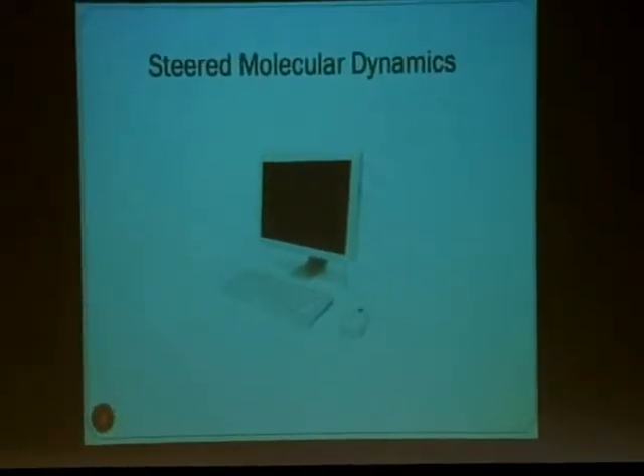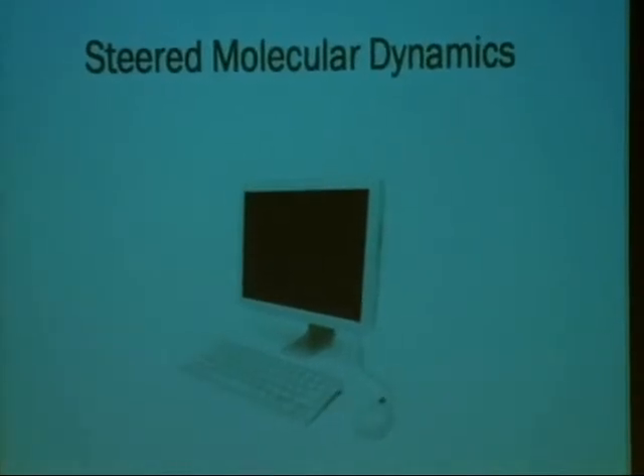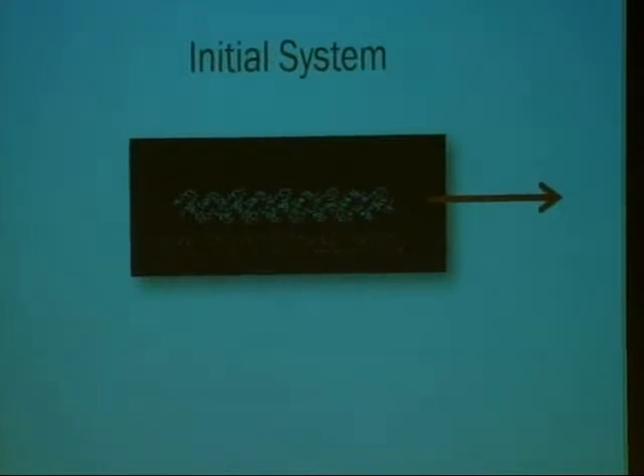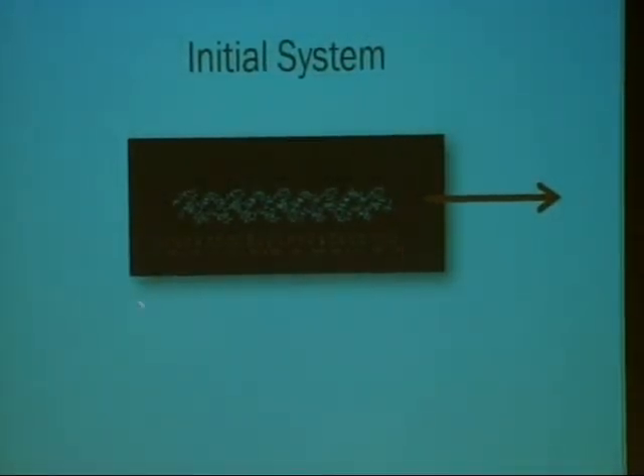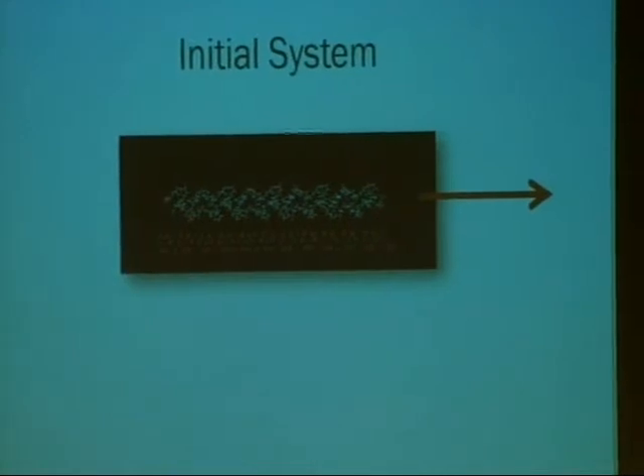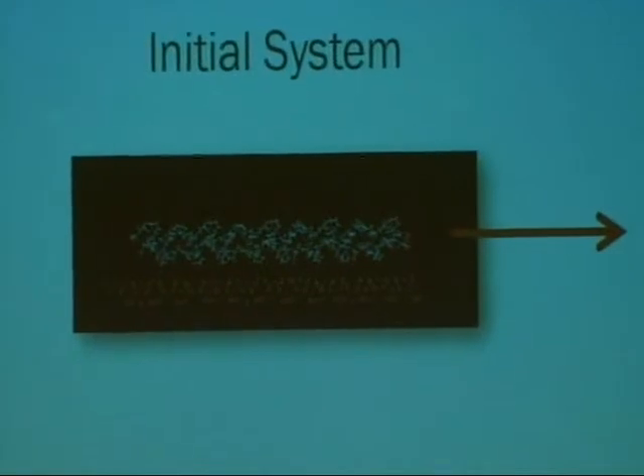To do this experiment, I used steered molecular dynamics simulation, which is a computational method that enables us to predict the behavior of a system when it is under load, combining both known experimental data as well as theoretical calculations. The initial system is the collagen molecule placed above the fixed hydroxyapatite. The collagen was then pulled in the right direction, and as it was sheared across the hydroxyapatite, we examined the changes in its mechanical behavior.